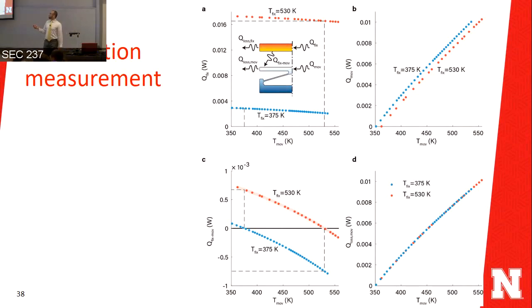So when you calculate the losses with the energy balance, you can calculate how much heat transfer there is between the two terminals. The impressive thing here is that the losses from the cold terminal, calculated at two fixed terminal temperatures, are co-aligning perfectly.